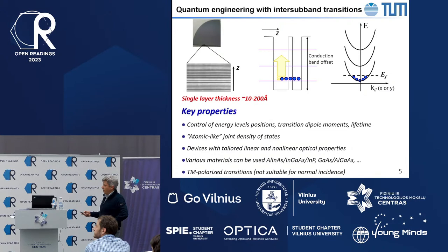But what you can also do is grow layers of semiconductor on top of one another. Some of these layers could have a large band gap, and some of the other layers could have a small band gap. And you can grow these layers with extreme precision, down to a few angstroms in thickness, essentially monolayer by monolayer. And by controlling the thicknesses of these materials, you can confine electrons in quantum wells.